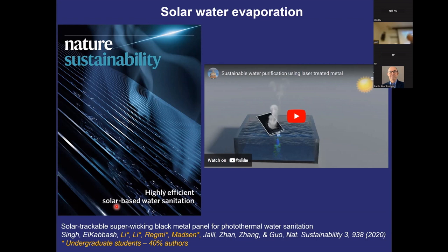Well, you might say this is insane. You are breaking energy conservation. It turns out not. That's why I'm saying this is a really exciting area. We started to notice that when the water is pulled up into a thin film, it also changes the intermolecular bonds. And that allows the water to evaporate in a different form, not the bulk water enthalpy anymore. So we start thinking the efficiency goes to 200%, 300%, 400%, just an insane amount of efficiency.